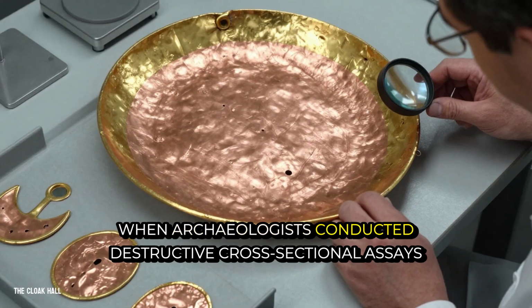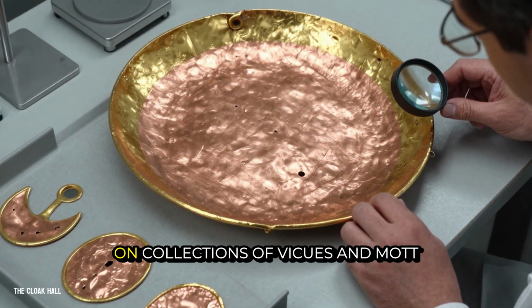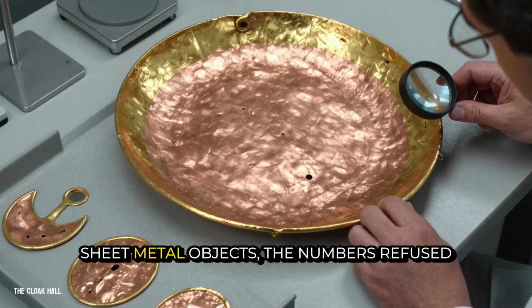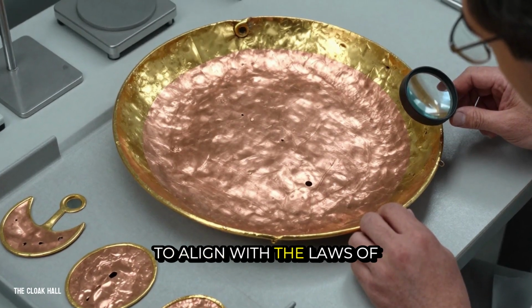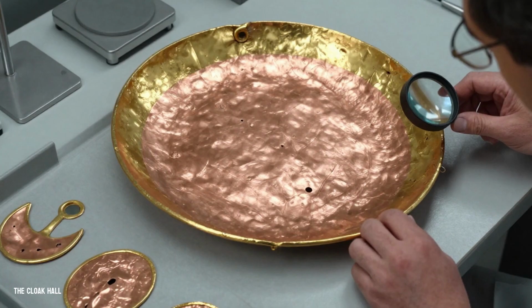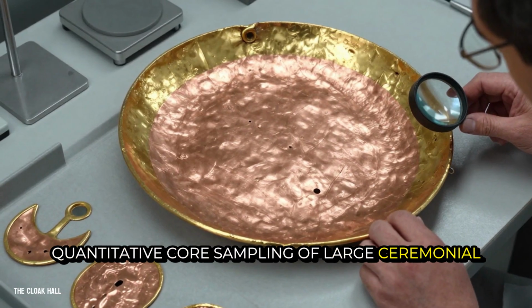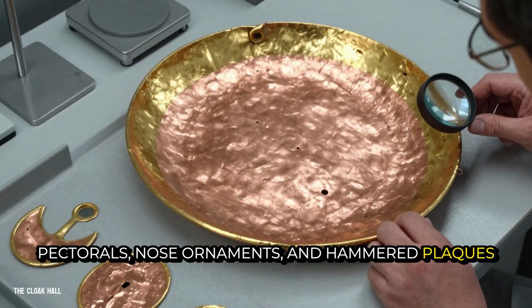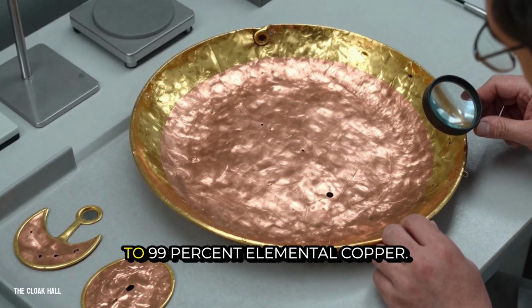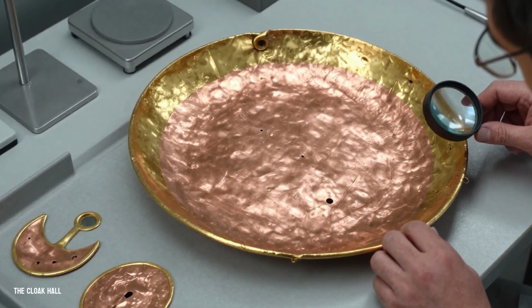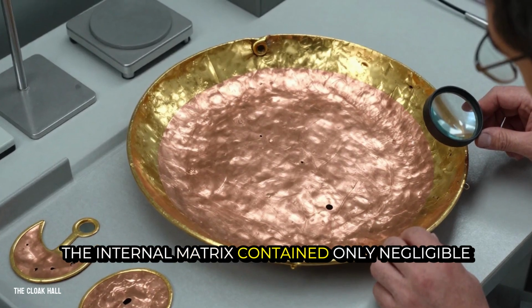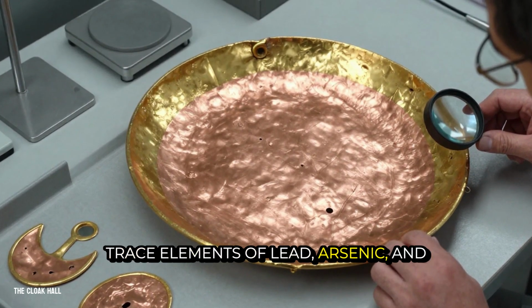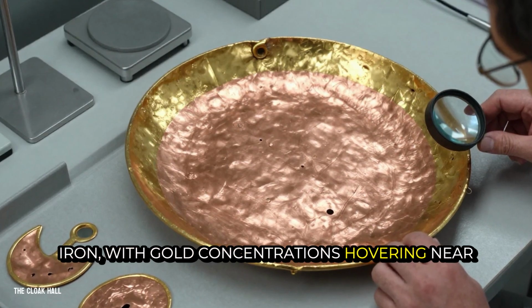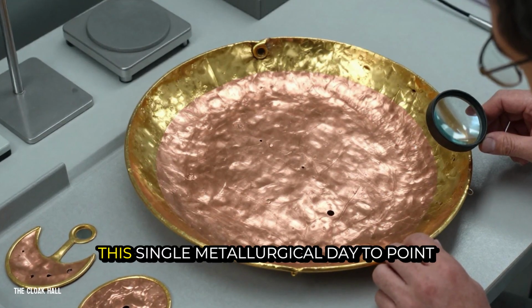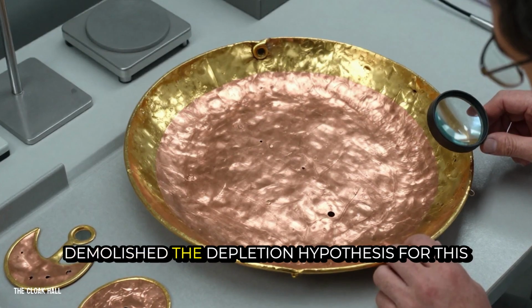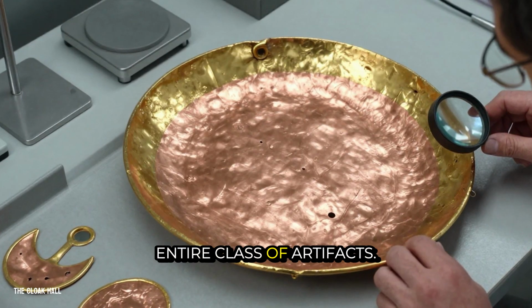When archaeometallurgists conducted destructive cross-sectional assays on collections of Vicús and Moche sheet metal objects, the numbers refused to align with the laws of depletion gilding. Quantitative core sampling of large ceremonial pectorals, nose ornaments, and hammered plaques revealed base metal purities exceeding 98 to 99% elemental copper. The internal matrix contained only negligible trace elements of lead, arsenic, and iron, with gold concentrations hovering near absolute zero. This single metallurgical data point demolished the depletion hypothesis for this entire class of artifacts.